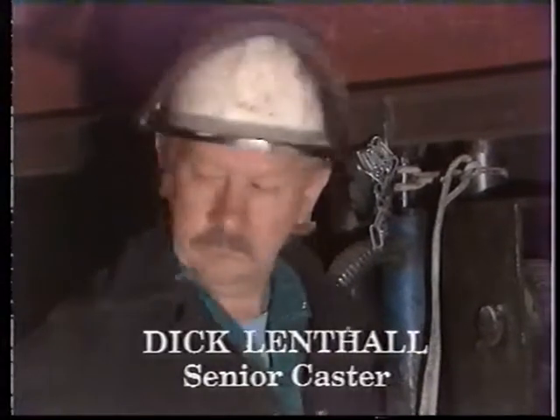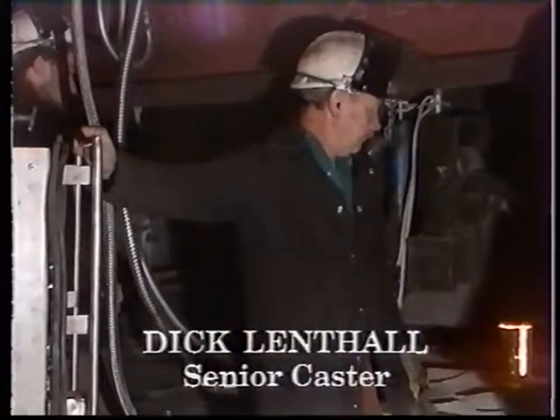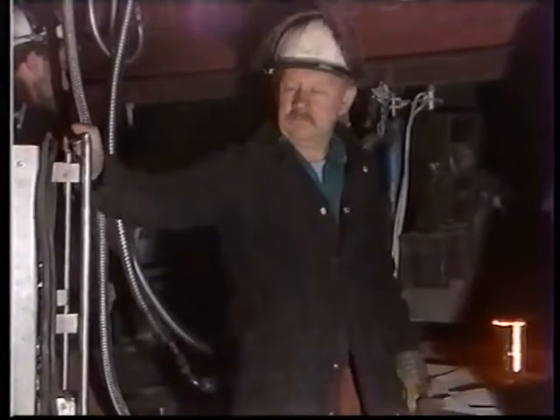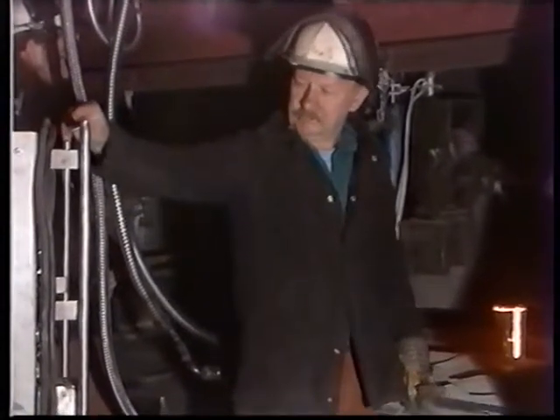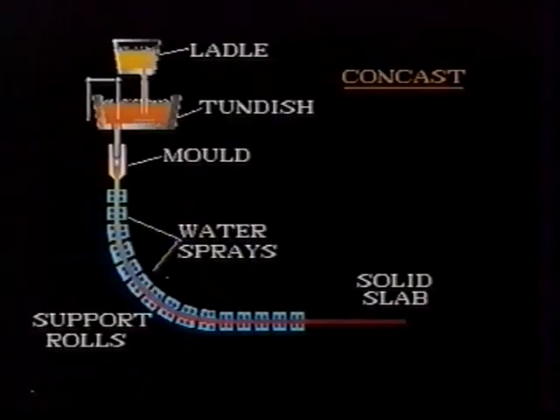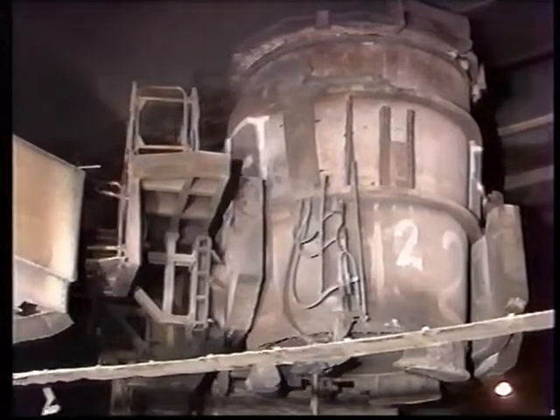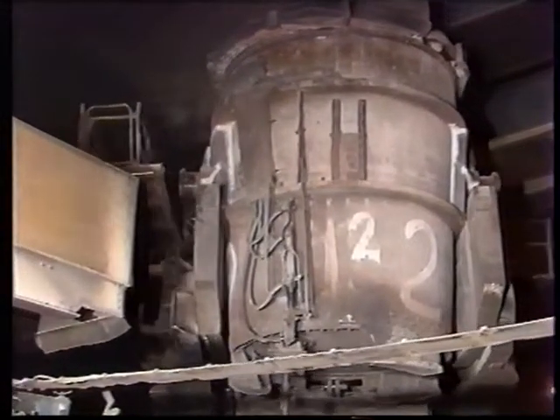The liquid steel comes here straight from the AOD vessel. We pump argon through it at the flushing station to bring the steel down to the right casting temperature. The steel is then poured into the casting machine through a tundish. From the tundish it flows into the mould through a submerged entry nozzle, where it is progressively drawn down the machine and slowly cooled. When the steel emerges from the machine, it is cut to required lengths.